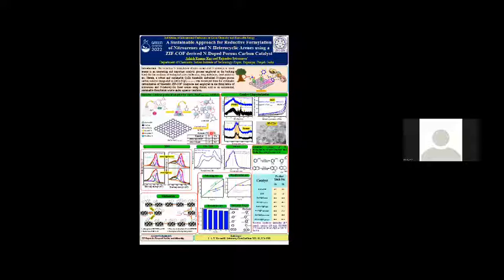By adding the COF, the pyrrolic kind of nitrogen got increased, and that's why the pyrrolic nitrogen has the ability to hold the metal atoms. Then after synthesizing this, the material was carbonized at 900 degrees Celsius, and the zinc metal starts to evaporate.